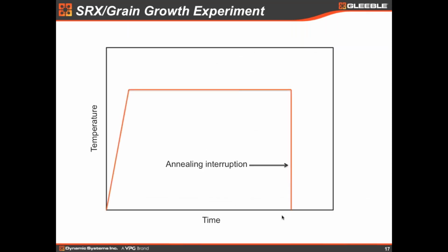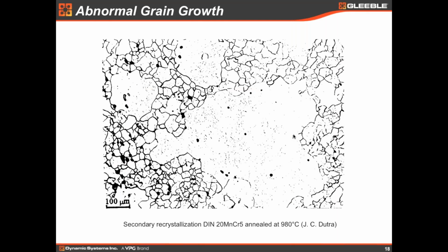So this is an example of the time temperature graph for a static recrystallization and grain growth experiment, where we have a ramp to temperature and then time at temperature, and then we interrupt the annealing by quenching or just turn off the heat. So this is a very simple experiment to produce reliable and uniform and reproducible recrystallized samples. So I want to show now grain growth. We show the curve, that graph for normal grain growth.